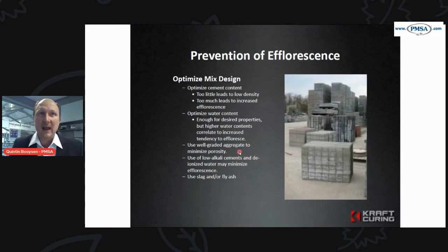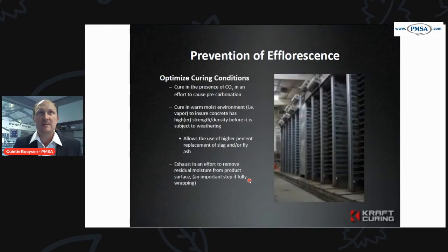Use well-graded aggregate to minimize porosity. Use low-alkali cements and de-ionized water; this may also minimize efflorescence. And the use of fly ash or slag can also be useful in minimizing efflorescence.